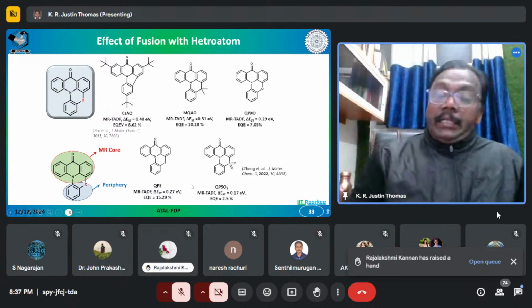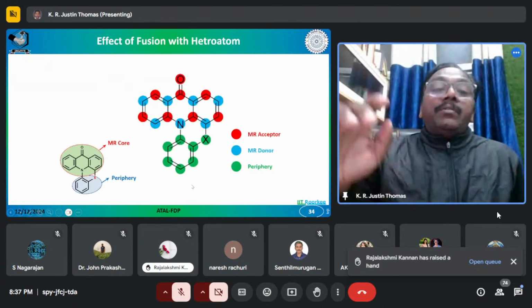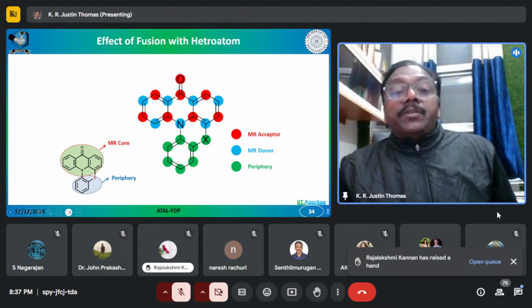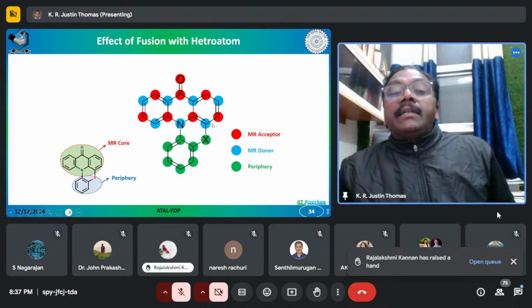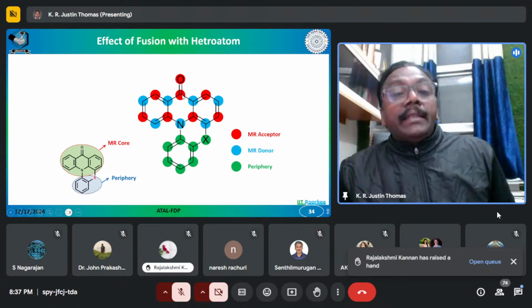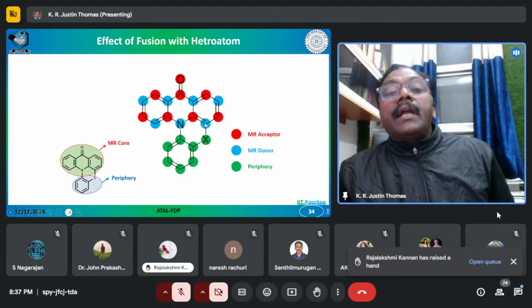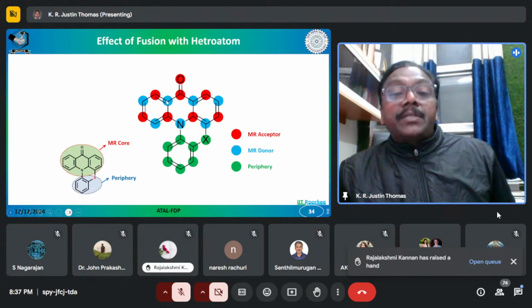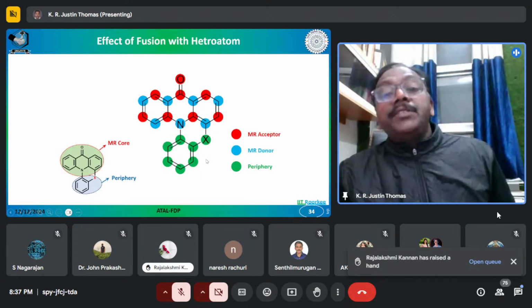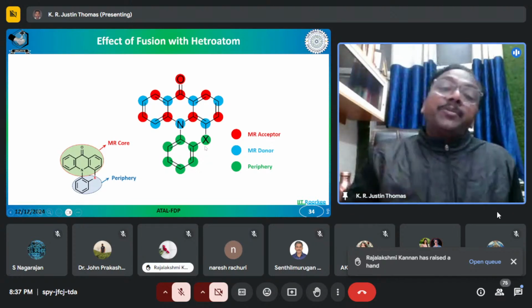Okay, and when you look deeply at these molecules, you can see that the MR acceptor is mainly on the carbonyl and then alternating atoms, and then the MR donor characteristic is mainly on the nitrogen and the alternate atoms, which are denoted here as blue. And then the periphery generally contributes to the donor.